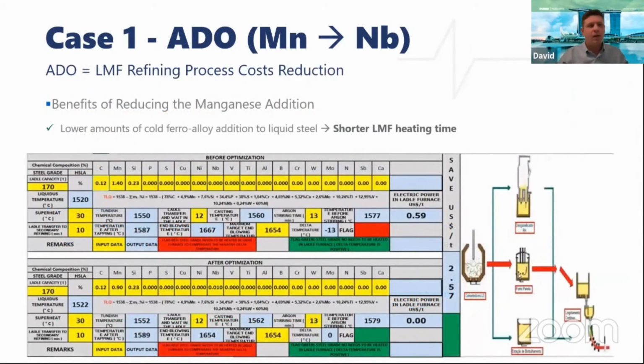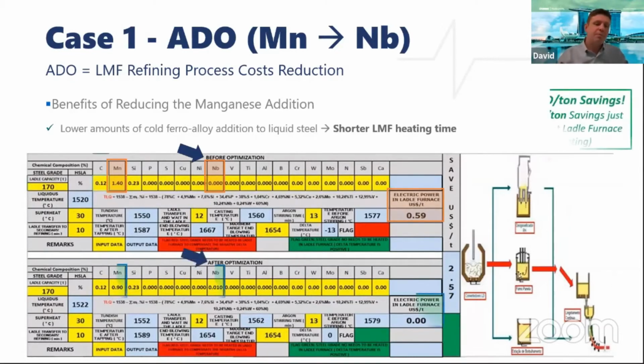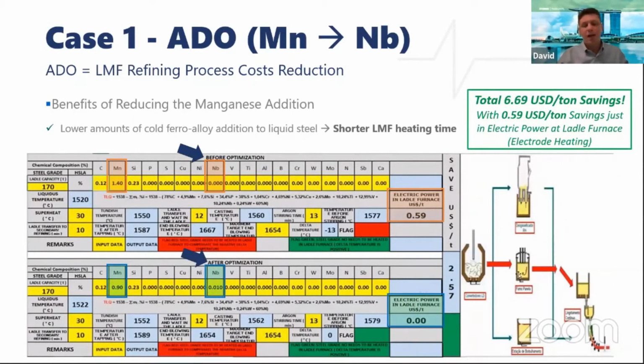This is a calculation that we had on the extra or side benefits of reducing the total ferromanganese addition. Right. In the beginning, this chemical composition had 1.4% manganese and no niobium addition. Due to the manganese cold addition, the thermal allowance is reduced. Therefore, you need to increase the temperature by heating up the molten steel with the use of electric power and graphite electrodes, and that was spending about 59 cents of a dollar per ton. As you added 100 ppm of niobium and managed to reduce the total manganese addition, the thermal allowance was enough without the use of the electrodes to run the heat at the correct temperature for transfer to the ladle. That saved 59 cents more on top of the $6.10 per ton that we had before, increasing to $6.69 per ton savings.